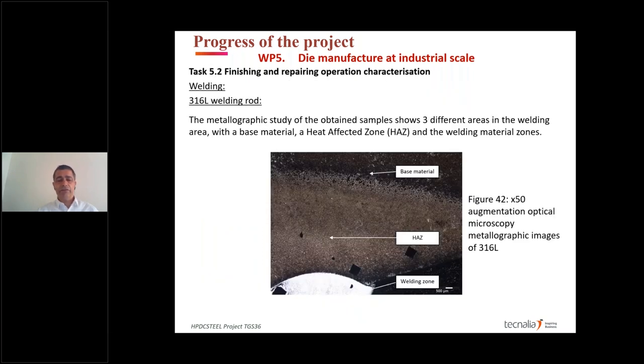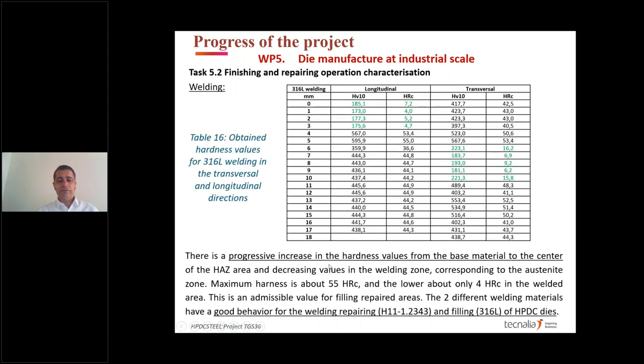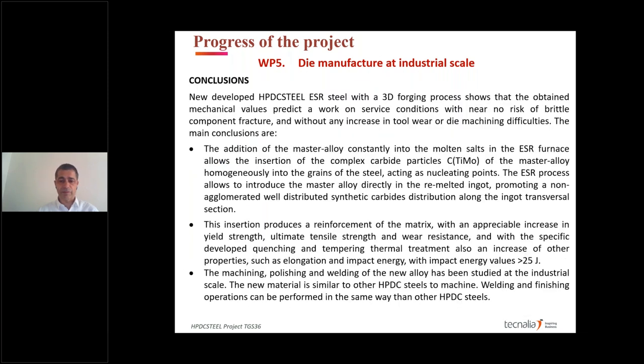And in the case of filling with the stainless steel, we see the difference between the base material, the heat affected zone, and the welding zone, as if they were different materials. The same hardness measurement, and here we have an area with very low hardness values, but this is common in filling materials for high pressure die casting die reparation.